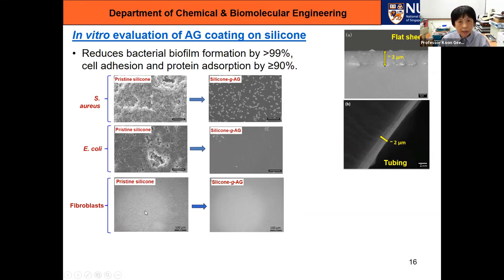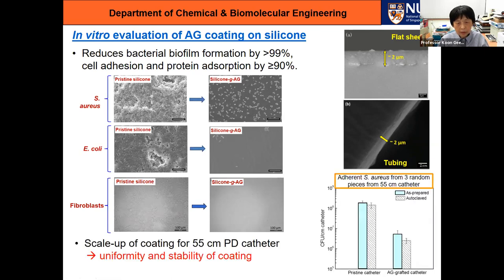Because this peritoneal dialysis catheter is very long, about 55 cm, we have to make sure that it is uniformly coated. So what we did is take the coating and cut out 3 random pieces along its length and carry out the antimicrobial assay to see what error bar we will get. This light blue bar, the first one here, is for the pristine catheter, so we have a high bacterial load. And this is the one that's been coated with agarose. So we have about 2 orders of magnitude reduction. And you can see from the size of the error bar that it's not big. So that means the coating is probably uniform.